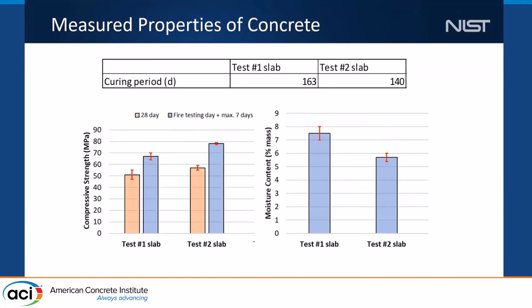So this slide basically shows the measured properties of the concrete. Test number 1 and 2 floor specimens were actually cured for 4 to 5 months before fire testing. And these bar charts basically summarize the compressive strength measured at 28 days and around the fire testing day, and also the moisture content before the fire testing.